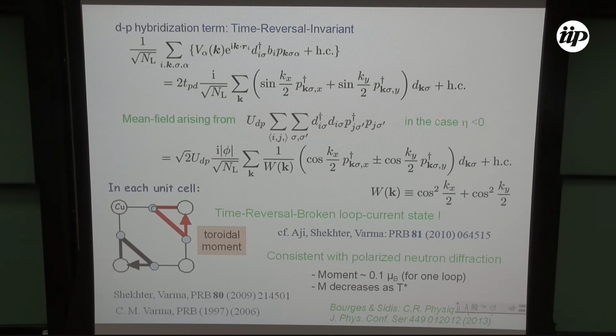For example, in the case where eta is negative, the mean field term is reduced to this kind of expression. This is time reversal symmetry breaking because i becomes minus i, and cosine kx and cosine ky are invariant. So the time reversal symmetry is broken. Actually, this state is the same as the time reversal broken loop current state like this, which is discussed in this paper in detail. This is a toroidal moment, which is consistent with the polarized neutron diffraction reported by the Bourges group.